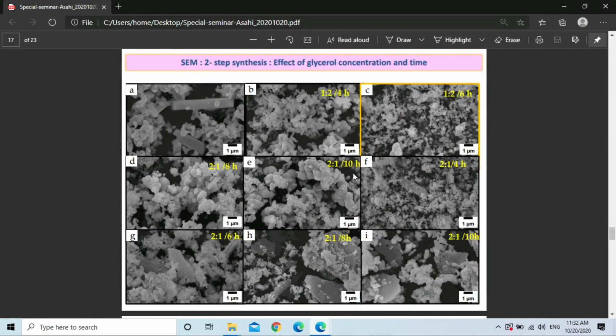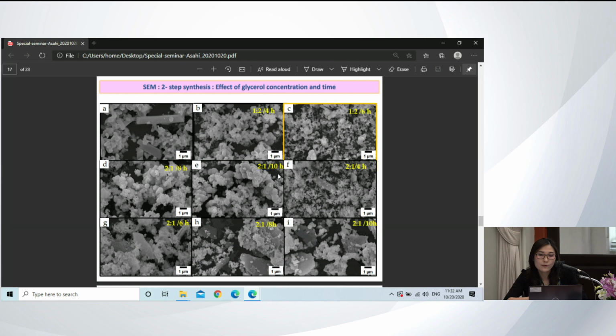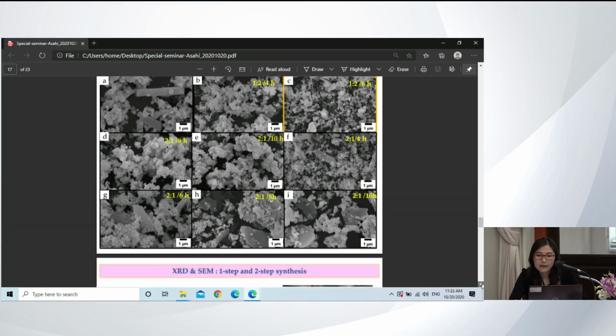So here you can see the morphology of sodium tantalate produced from the two-step synthesis. The morphology of the particle becomes spherical, compared to the previous one-step, which is a cubic shape. The ratio of glycerol and water and the time have an effect on the morphology, the dispersivity, and also the homogeneity of the particle.